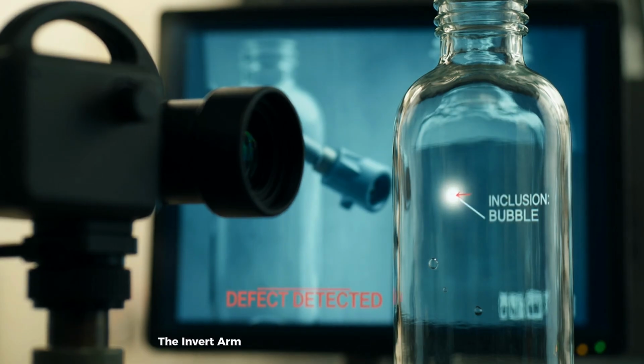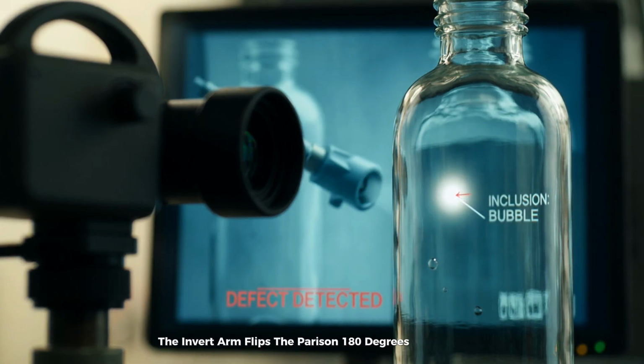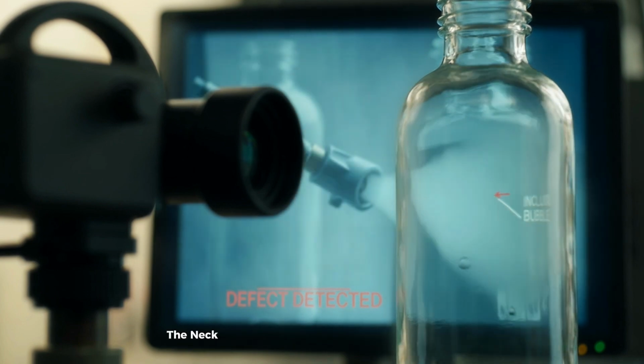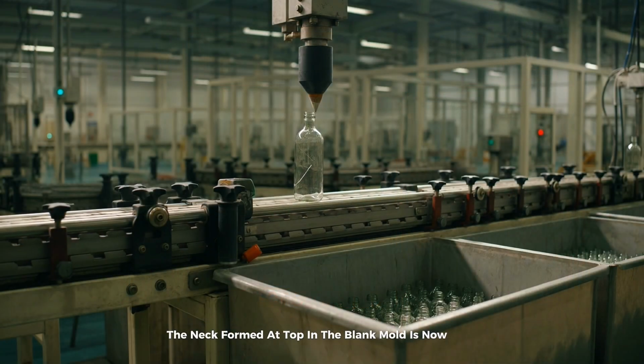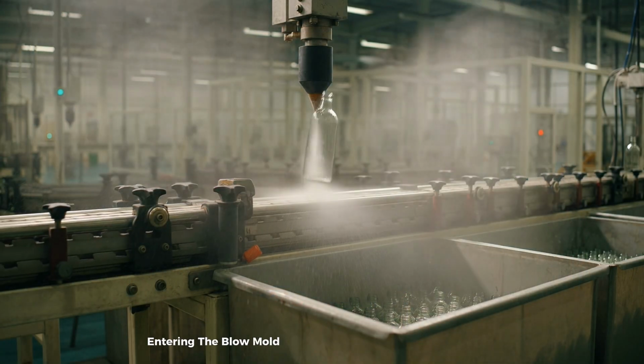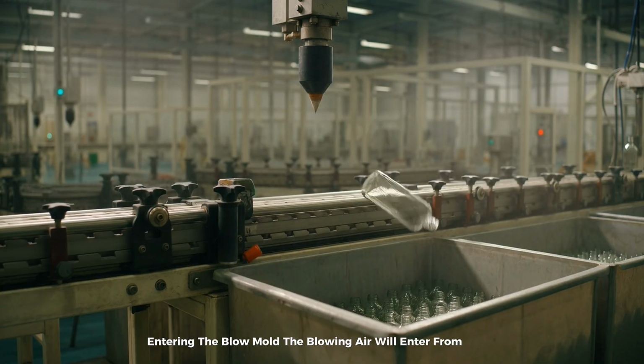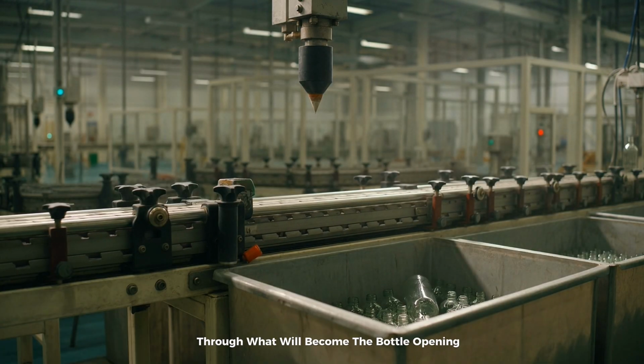The invert arm flips the parison 180 degrees during transfer. The neck formed at top in the blank mold is now at the bottom entering the blow mold. The blowing air will enter from the top through what will become the bottle opening.